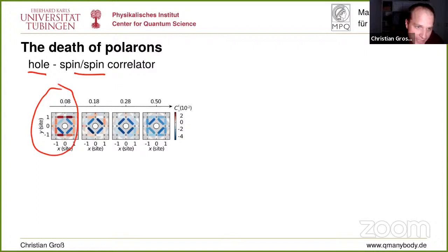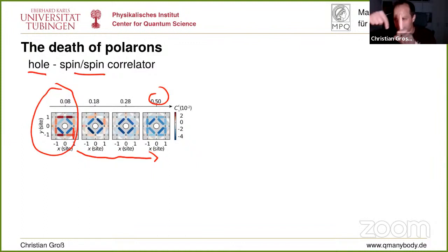And what you see here at low doping is this polaron signal that I was arguing about already and telling you about before. And we see now basically that when we increase the doping, that polaron signal really drastically changes. So let's look at 0.5 doping. So this positive correlation that we have here on these nearest neighbor bonds really changes sign and goes to negative. And what we always calculate here, this correlator, a bit for the experts, is always a fully connected correlator. So what is out of the correlator is any contribution of a 2-point magnetic correlator. Meaning basically, if this thing has the opposite correlation than what you would expect in the background signal, then that really means that this correlation is flipped by the presence of that hole there.